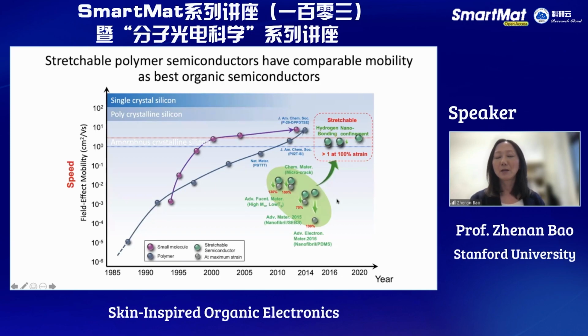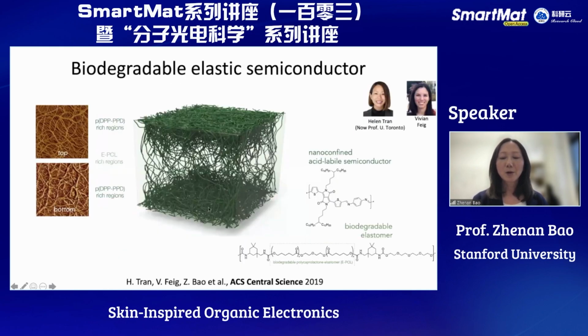So with these developments, then the charge transport for stretchable polymer semiconductors. Initially, when we first started this work, there were a few reports, including our micro-cracked system and some other systems. Even though nanofiber was used, the nanofiber was mixed with elastomer, where the elastomer will impede the charge transport. And in our case, with these new design rules, now we're able to take the charge transport to a similar level as those of the best polymer semiconductors. And we're very excited about this approach because it's quite general. As long as we can induce these nanostructure formations, we can not only enhance the charge transport, but add new functionality.